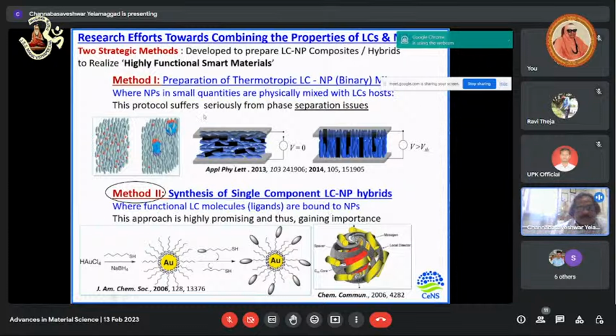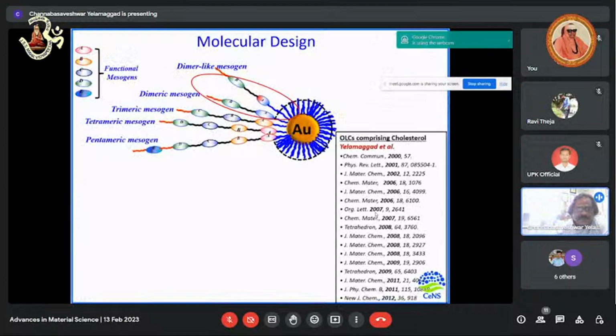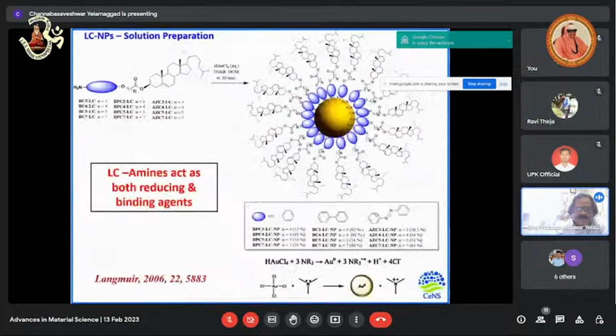There are 2 approaches. One, you take gold nanoparticles and mix them physically, but there is a phase separation problem. The other is a method wherein you synthesize single-component LC-NP hybrids, where functional LC molecule ligands are bound to a central gold scaffold. This approach is highly promising. That's exactly what we have done. Let me skip all these things and go to what we have done exactly.